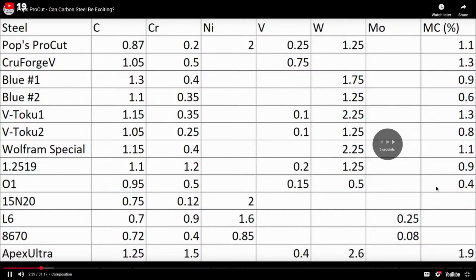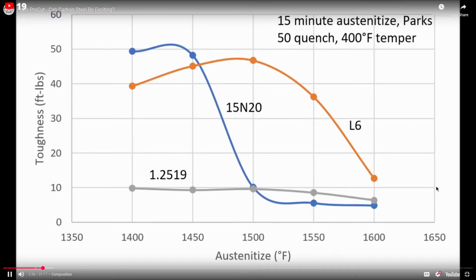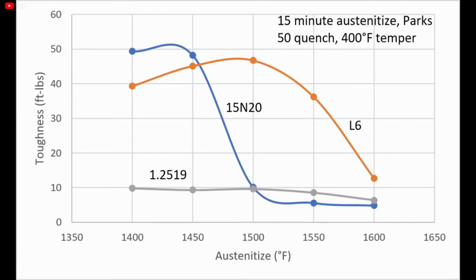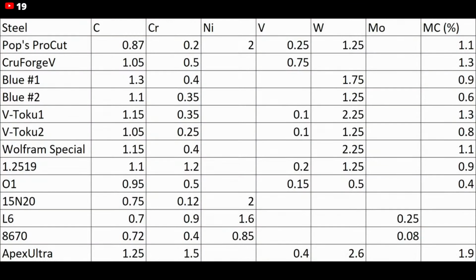Also, the carbon forge heat sees grain growth already at like 1500 degrees Fahrenheit, and then its toughness drops off a cliff. So if we kept the tungsten and vanadium in check, to reasonable levels, we could maintain good forgeability. It would be easy for beginners to use, and we can have something that is really easy to heat treat in a forge and offers that good edge retention like other tungsten vanadium steels like Blue Steel or V-Toku or Wolfram Special or 1.2519. They're all kind of obscure steels. They're even kind of hard to obtain a lot of times, and they can be expensive.